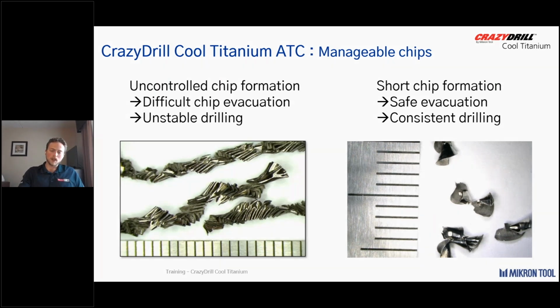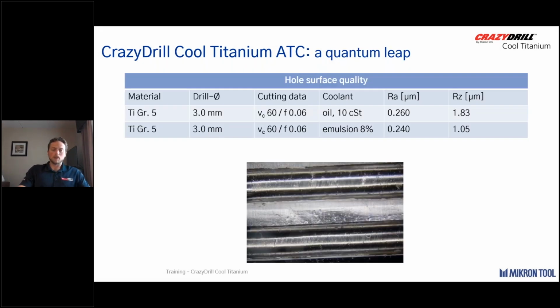So how do we achieve that? We've touched on the basics throughout this presentation, and we've also seen an increase in surface finish due to good chip formation. So not only is good chip formation going to parlay itself through evacuation, reliability of tool life, and consistent hole size because you're not rubbing, but it's also increasing the quality of the bore. So we see here a very fine surface finish, to the point where you could almost get away without a reaming operation if you have a low surface finish callout.